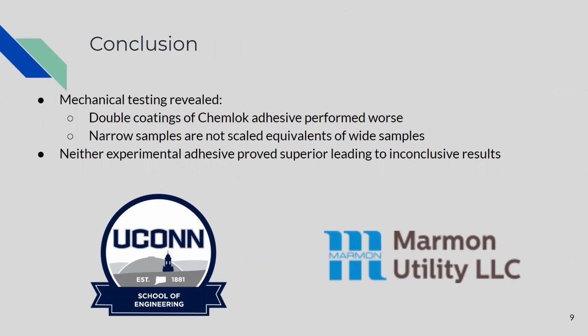In conclusion, the testing data revealed that double coatings of the Chemlok adhesives did not perform better than a single layer of the adhesive, and also the narrow samples performed in a weaker manner than the wide samples. Overall, neither experimental adhesive provided superior results, leading to inconclusive results as to which adhesive should be selected.